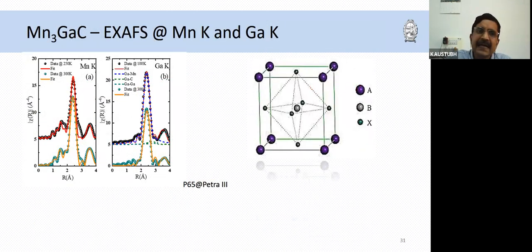Okay, so we did EXAFS, and these EXAFS were done at P65, and we have done both manganese and gallium edges. And the reason for this is very simple. If you look at the perovskite geometry, if I take, for example, manganese, the first neighbor is carbon, which is at A/2, half the lattice constant. And the second neighbor is gallium and manganese at the same distance, that is A/√2.